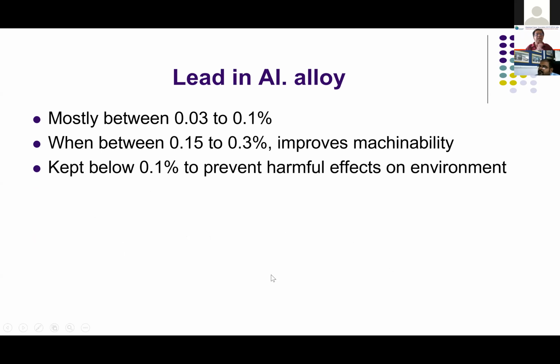Lead. Again, these are all, I would rather put it in impurity or minor elements, mostly between 0.03 to 0.1%. When between 0.15 to 0.3, it is deliberately added, it improves the machinability, right? But we keep it below 0.1% to reduce the harmful effects on the environment at a later stage when the material is scrapped.